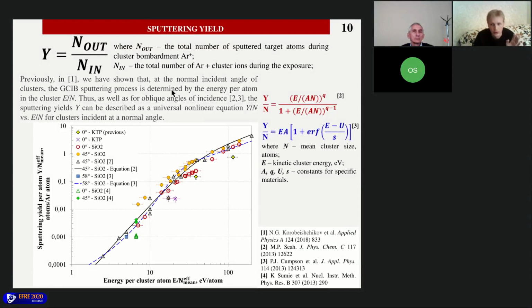The most important universal parameter of material processing is the sputtering yield, which in the general case is determined by the ratio of the number of sputtered target atoms to the total number of cluster ions during exposure.